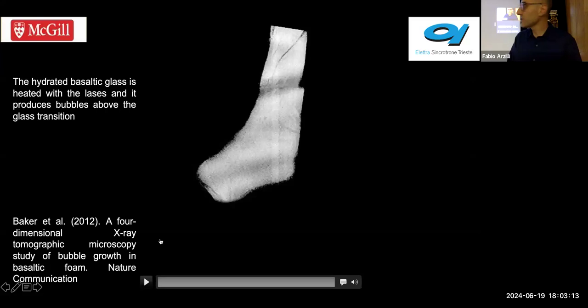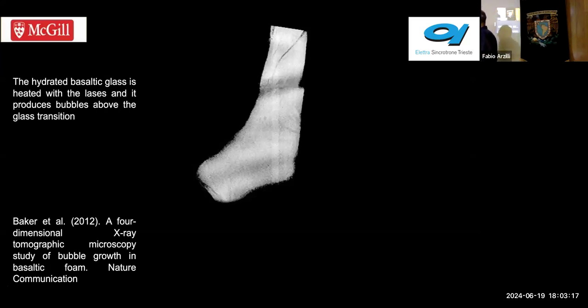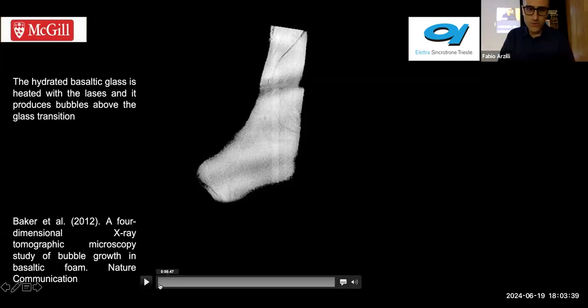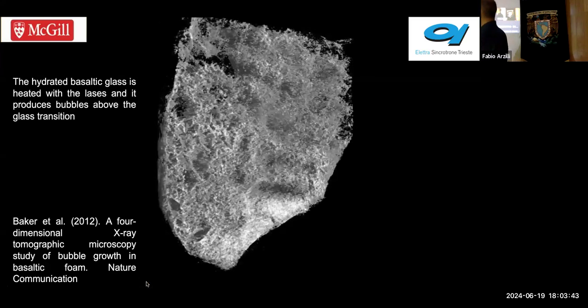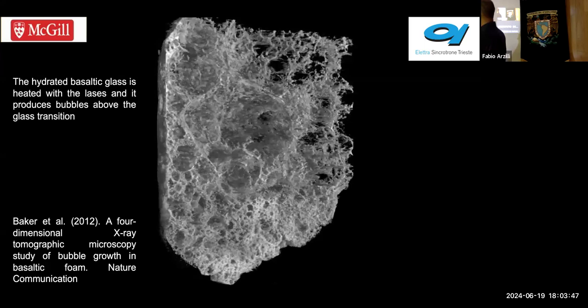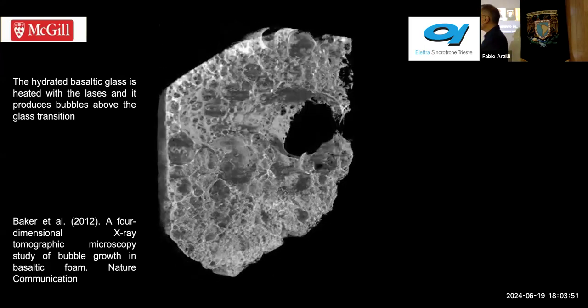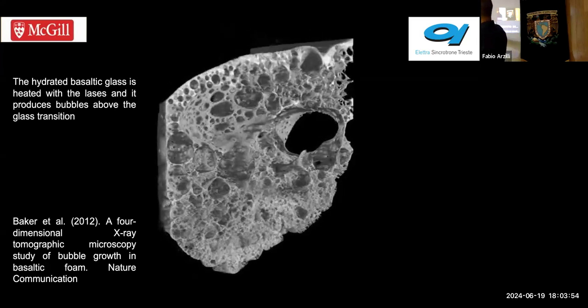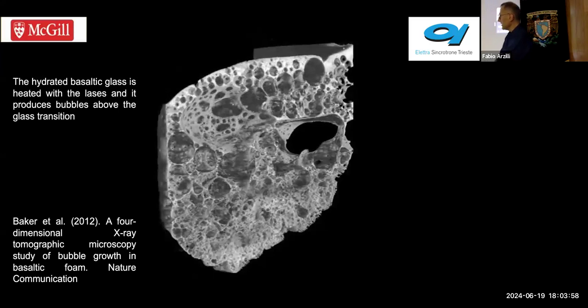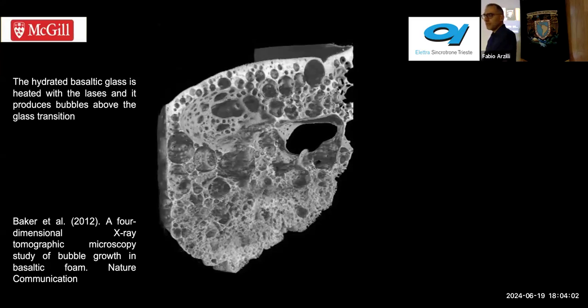This is the first experiment that was performed in 2012. This is a pioneering experiment performed by Don Baker at the Swiss Light Source in Switzerland, where he used basically a hydrous glass. This is a hydrous basaltic glass with 3% of water inside at ambient pressure, just heating up this glass with a laser and recording in real time. So the vesiculation that you see is quite fast. It's within 18 seconds. This video is just 10 seconds. And basically, heating up above the glass transition, you obtain this kind of scoria. Okay, this was the first experiment investigating vesiculation in real time at ambient pressure, just heating.